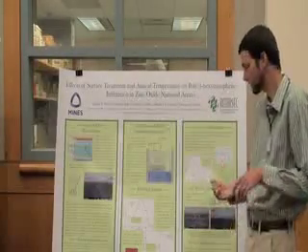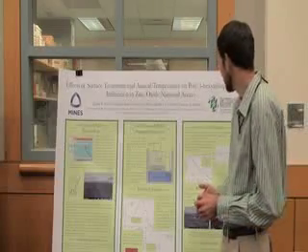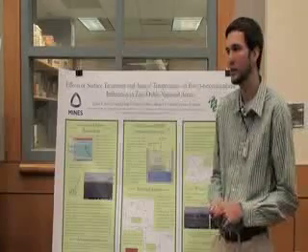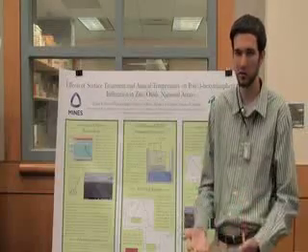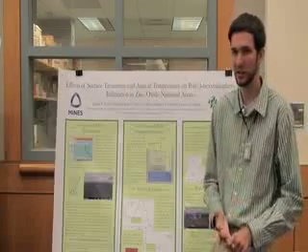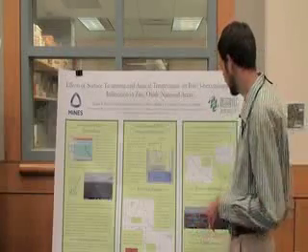So then we moved on to chemical surface treatments. We treated our samples with octadecane thiol, octadecyl triethoxysilane, and phenyl triethoxysilane. We found that the PTES, or the phenyl triethoxysilane, had little effect on the infiltration or the ordering of the polymer. However, the other two, the octadecane thiol and the octadecyl triethoxysilane, increased the ordering of the polymer, although it did not increase the amount of infiltration. So you can see in this area here.